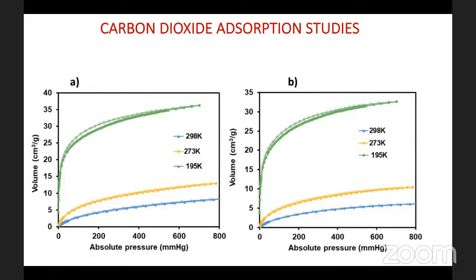And of course, interestingly, at 195 kelvins, the amount of carbon dioxide in both cases is very much comparable. I've looked at literature. You would expect the amount of carbon dioxide adsorbed by this ruthenium functionalized MOF to be less than that of the pristine MOF, because here you already have your ruthenium complex occupying the pores. That should reduce the surface area in which you are adsorbing your carbon dioxide. But in this case, they are very much comparable. And in literature, there are also reports in which MOFs, after functionalizing them, may have a higher amount of gas adsorbed onto their surfaces.